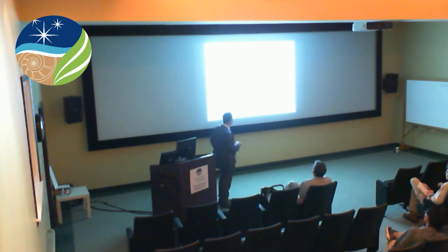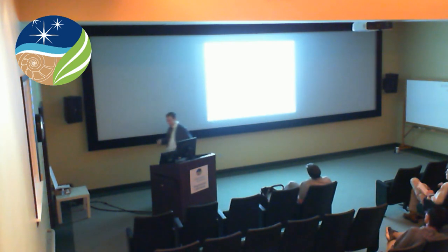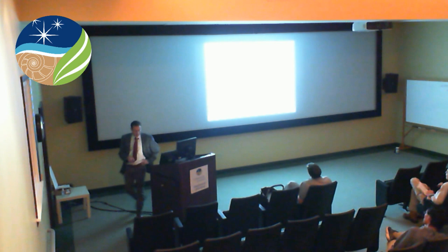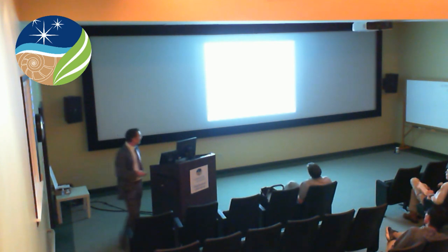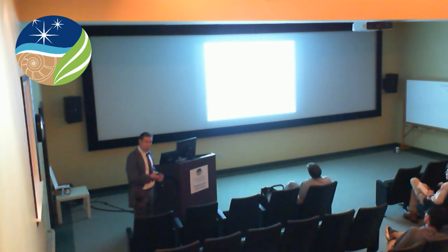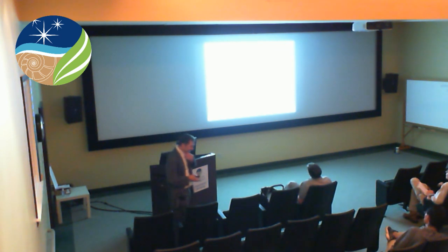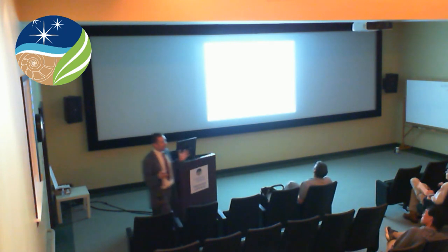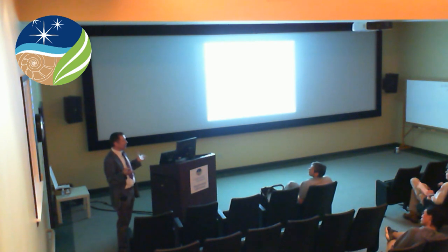This is kind of the overall idea of what's happening. This is just a schematic that I drew, but basically when you apply a field along the x direction, the polarization is rotating from z to x, and finally it switches to Px, to the x direction, and then you lower the field and it goes back, there is a restoring force to go back the other way. And so that gives you this double loop effect here. And you have to think about it a few minutes before you see why that gives a double loop.